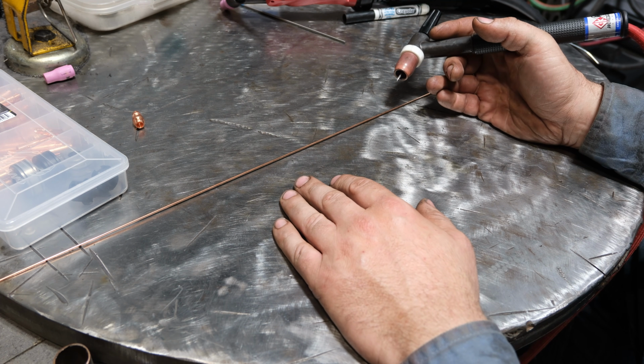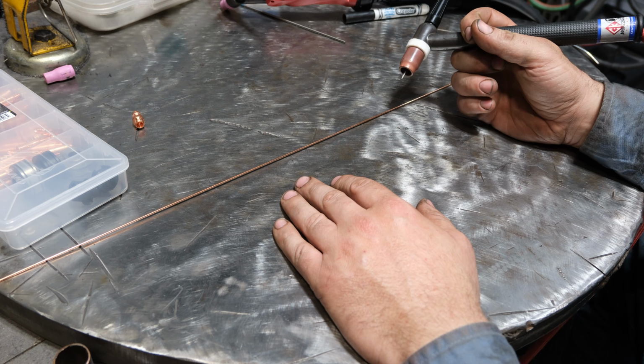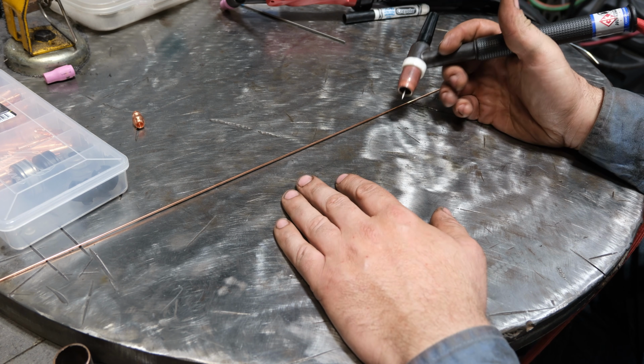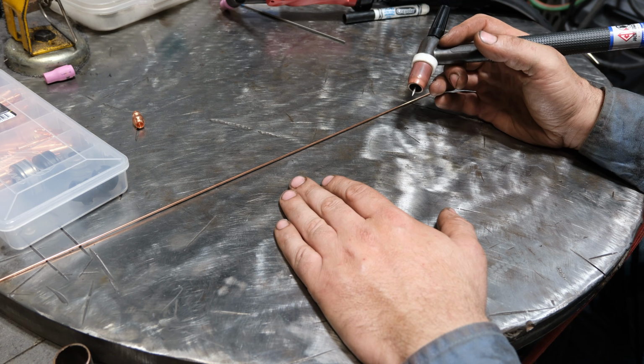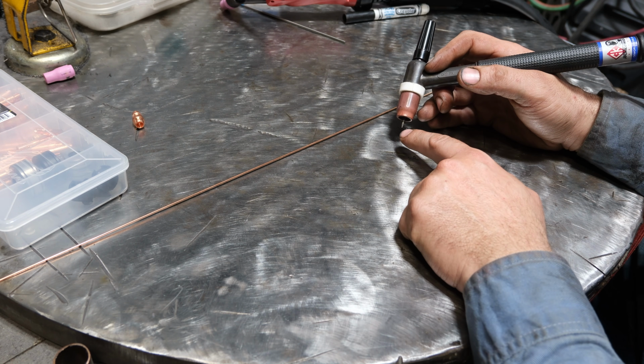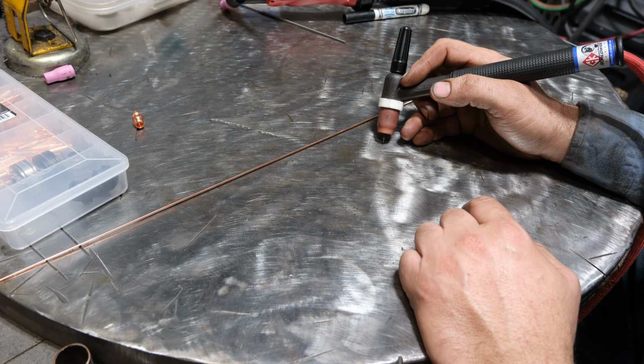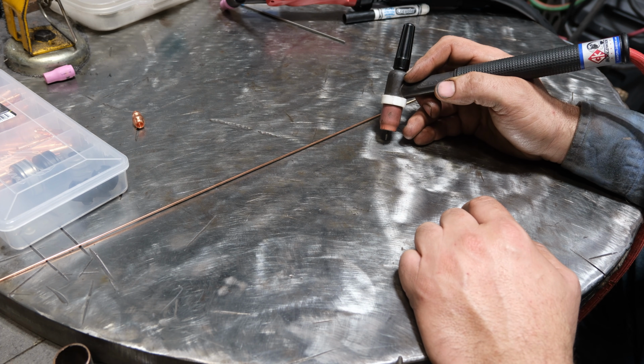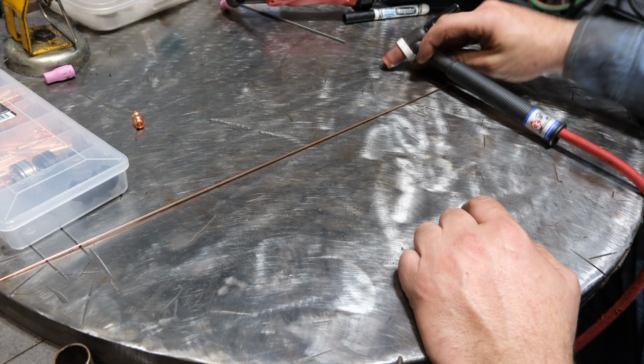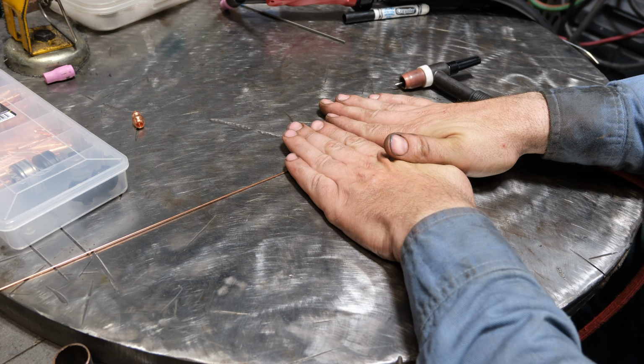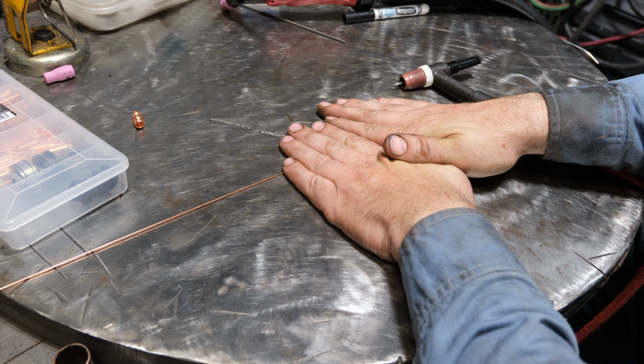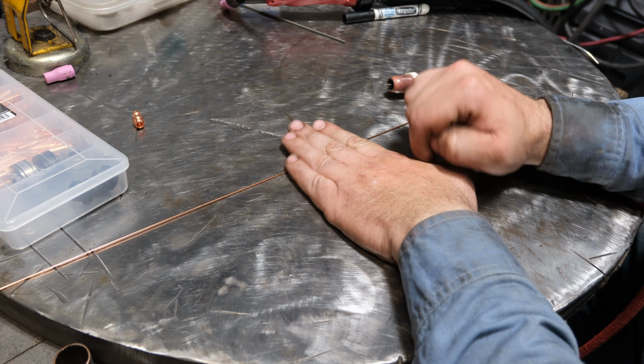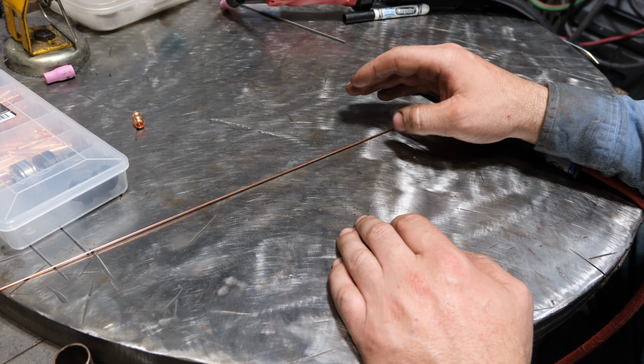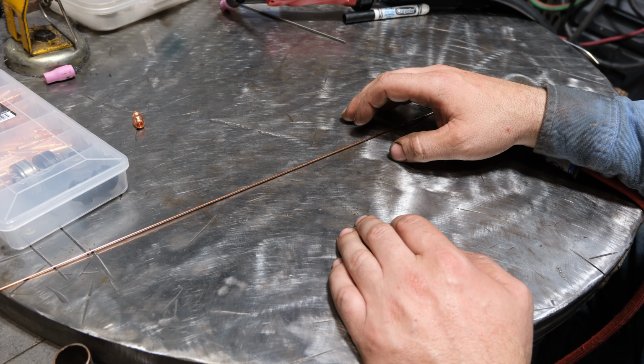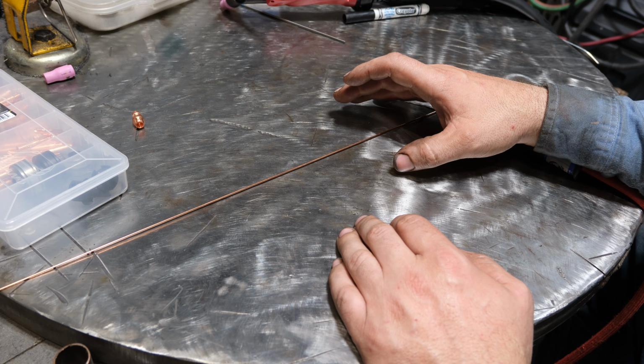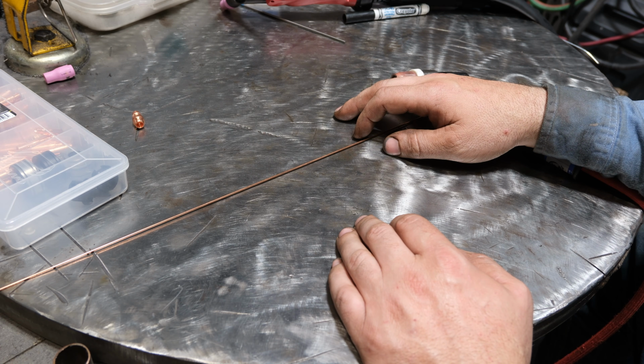With the MIG process, where you have a gun that feeds wire, and the wire is both the filler material and electrode, same thing with stick welding. Well, TIG doesn't deposit metal via the arc. All this torch is used for is more or less controlled heat. So you can use that controlled heat to weld two pieces of metal together in a lap weld or in a butt joint, where you can just fuse right down and not add filler material. Well, the problem with that is your weld is going to be pretty weak. You're going to more or less have just undercut, and depending on what you're building, that might break.